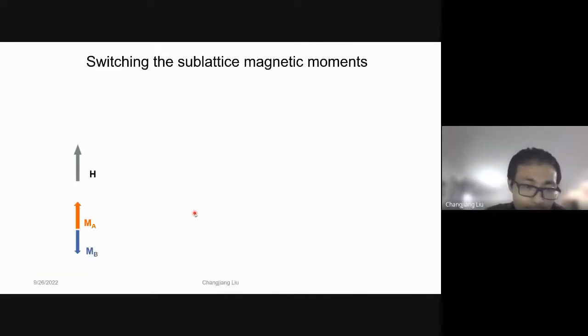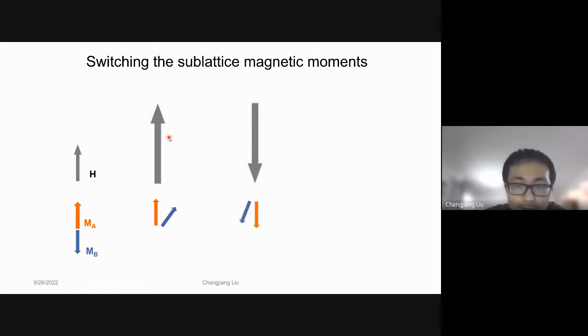To do that, suppose initially you have sublattices A and B pointing up and down respectively. Now we apply a high magnetic field, high enough to induce a spin-flop transition. And then we rotate the magnetic field by 180 degrees. So this flop state can follow the orientation of the magnetic field. And then we reduce the magnetic field. Eventually, we can flip the orientation of these two sublattices.